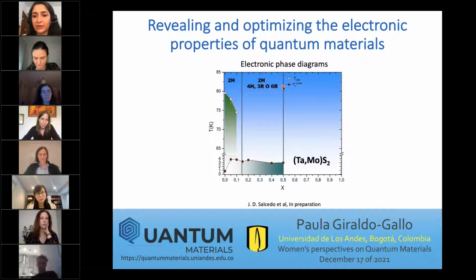So this is the tantalum disulfide material, and we are trying to see how we can strengthen novel quantum phases, like for example superconductivity in this material, in the background of competing electronic phases like the charge density wave in this compound. And we see that we can strengthen, for example, superconductivity by weakening the charge density wave in this material. And no matter the structural phase that we obtain for this compound, superconductivity is optimized. So maybe this is actually related to the disorder.